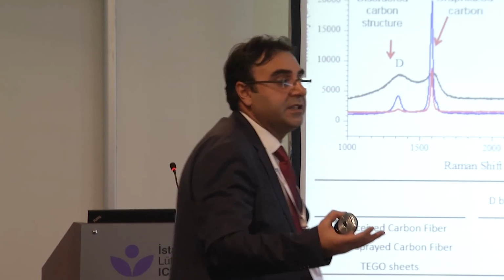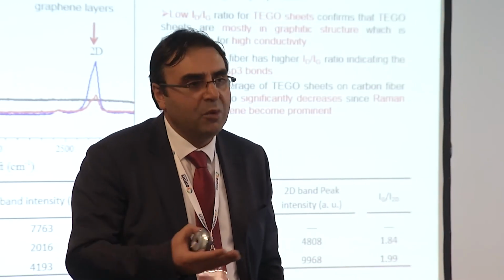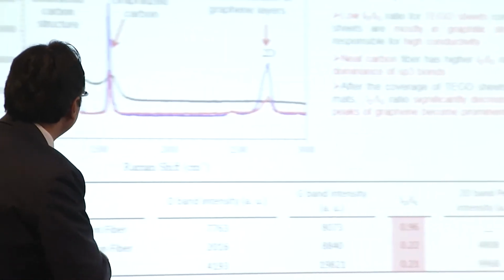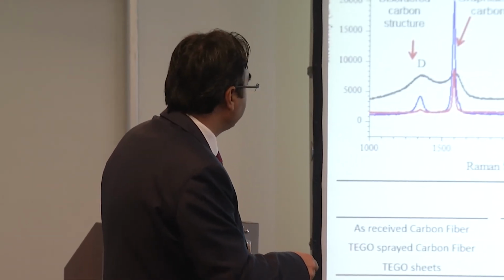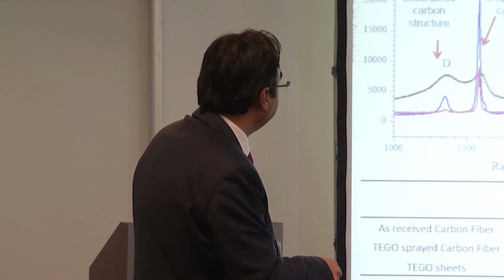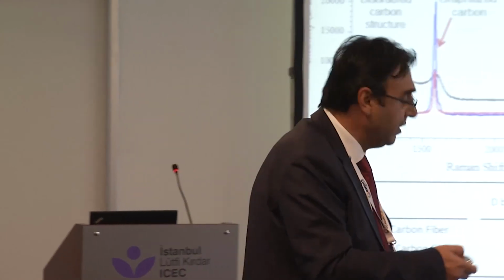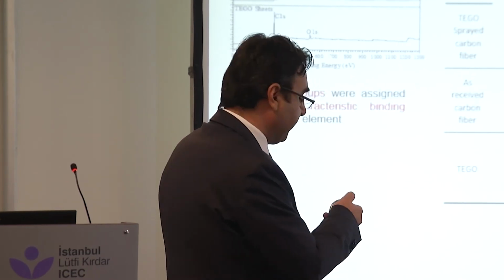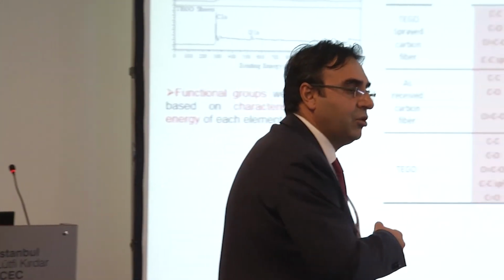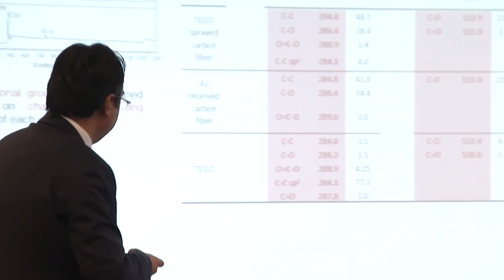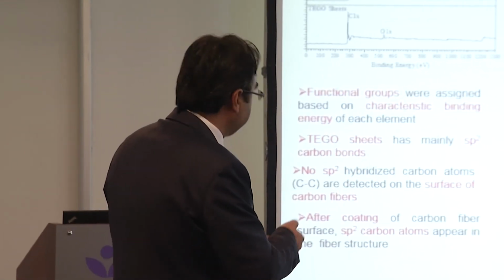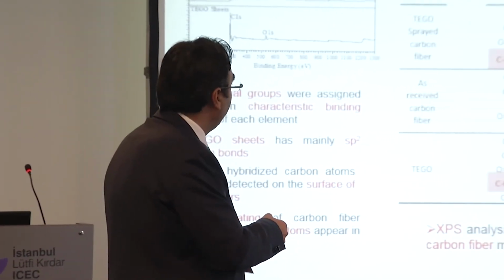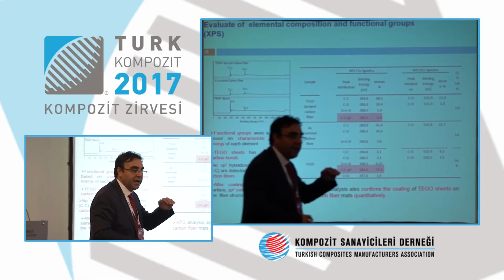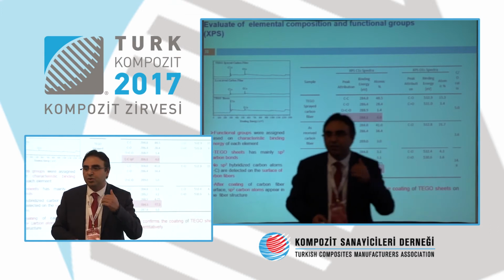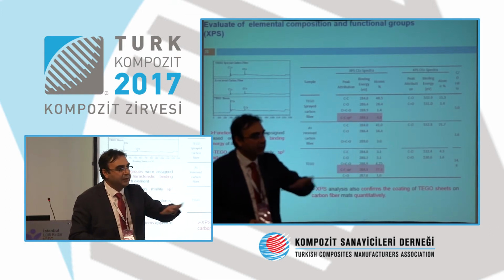And then we, of course, look at, just to prove our claim that we cover the surface nicely, the Raman of the surface. By Raman spectroscopy, by comparing the D-band and G-band intensity, we can show that we were able to cover the surface of our material. Also, just to ensure that this is not going to lead us in a wrong direction, we look at the XPS as well. This is a facility at Koç University that kindly performed this test for us. Looking at the sp2 bands, we show that our material is well covered by the thermally exfoliated graphene. So these characterization tools are performed to prove that we can nicely cover the surface of our material.